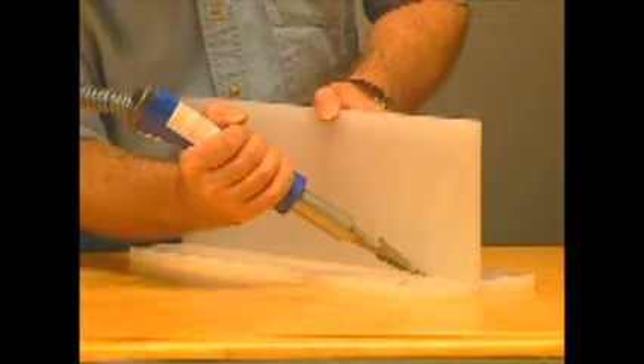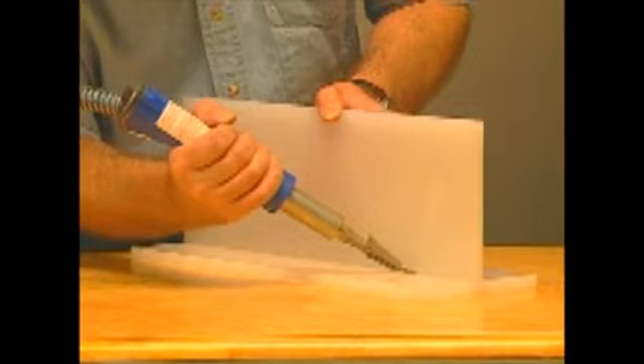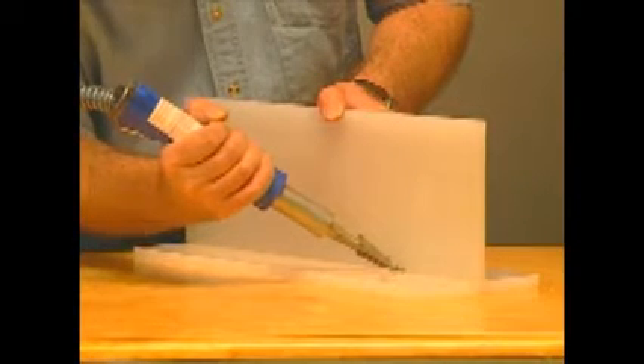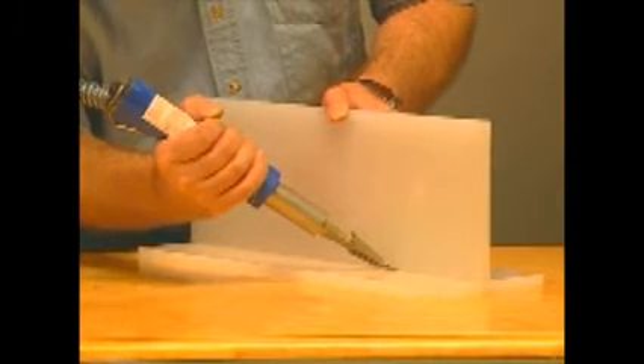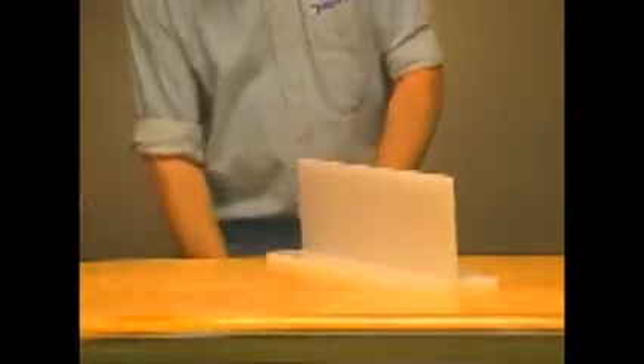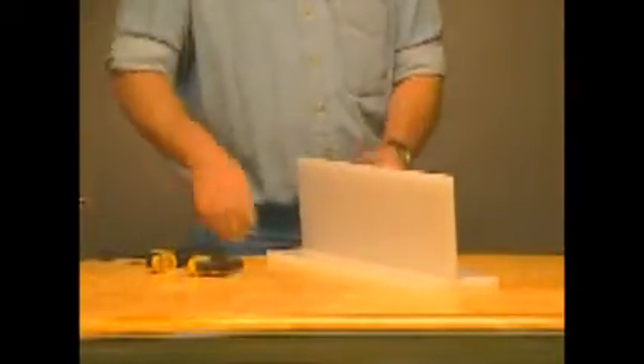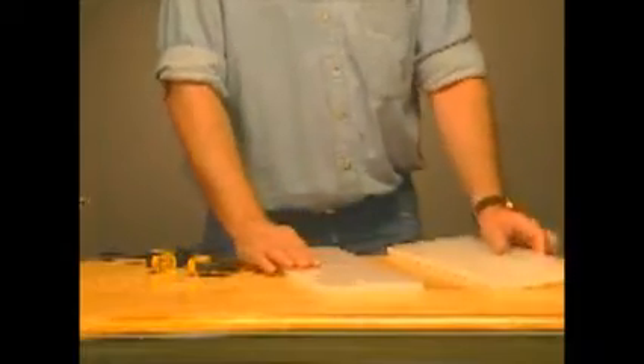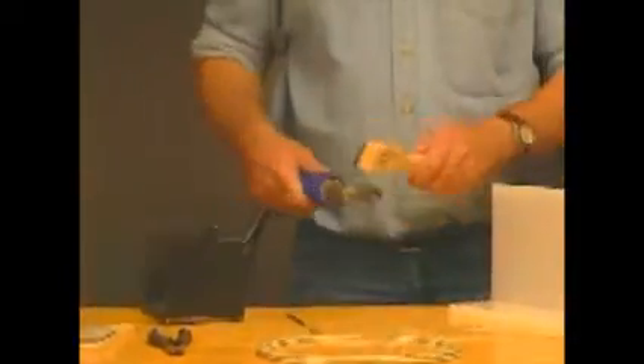In general, both sides should be tack welded to provide even distribution of heat and to keep warping to a minimum. Tacking does not add any strength. Should a piece be misaligned, a tack weld is easy to break apart, while a filler weld would have to be removed mechanically. After tacking, flip the tacking tip to the back in order to use the high-speed tip.